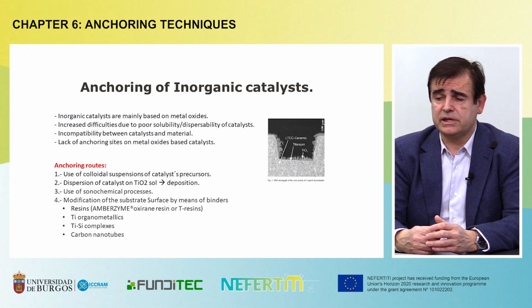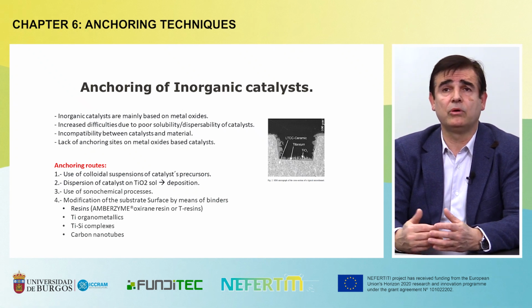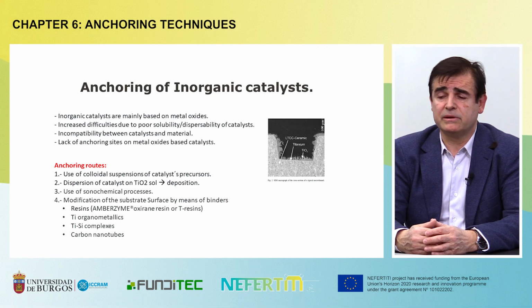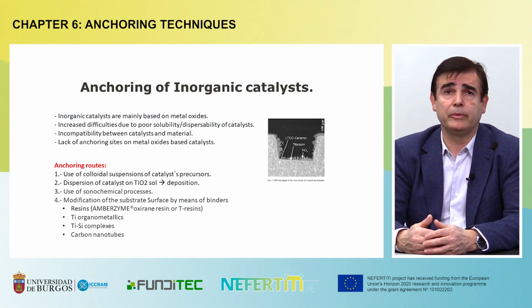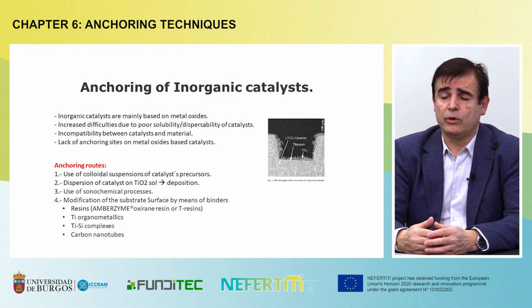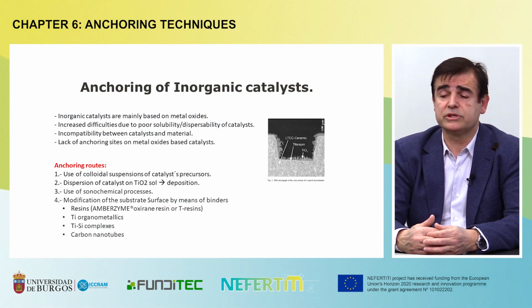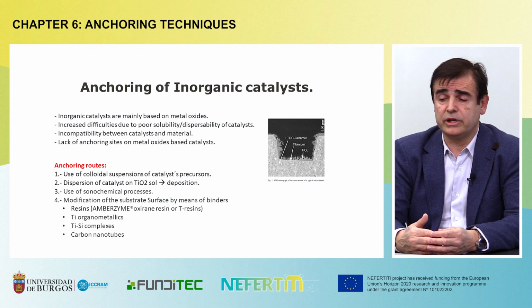Due to their chemical characteristics, they usually are oxides, and their low dispersibility makes them hard to dissolve or suspend. The lack of reactive points in that metal oxide makes it impossible to immobilize them by means of the already mentioned anchoring molecules that use surface functional groups to get fixed. The way to anchor the catalyst on the substrate is often by simple dispersion of the oxide that makes up the catalyst in the hollows, pores, channels, and surface of the substrate on which it is deposited.